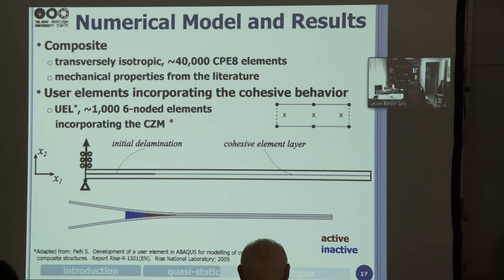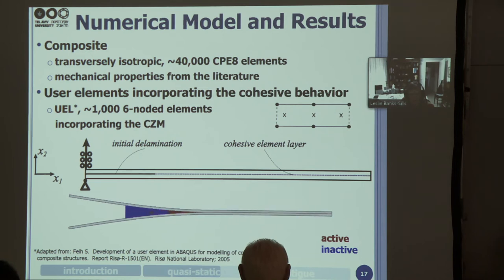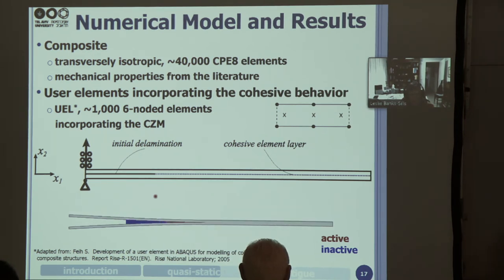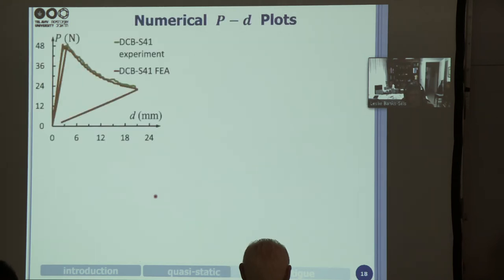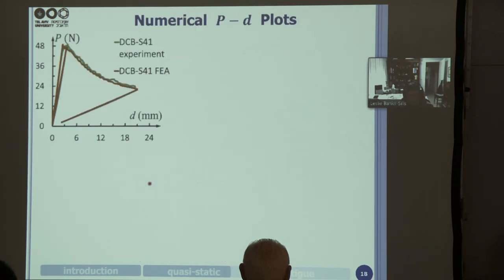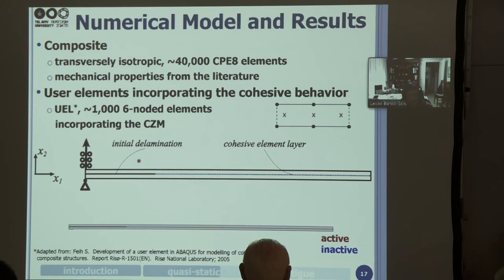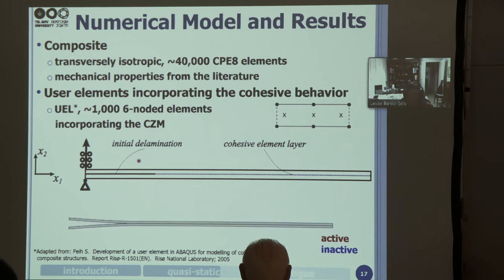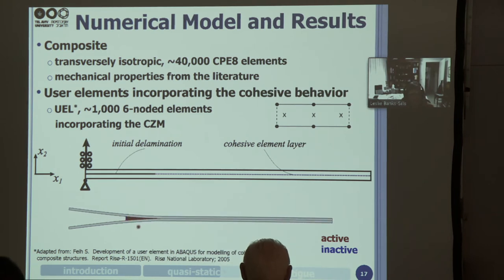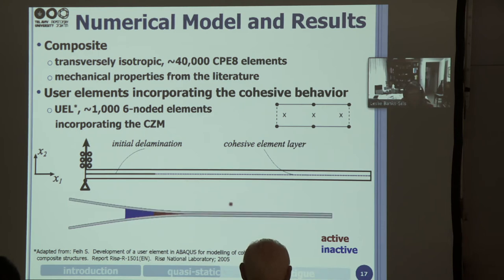And you can see now the propagation, the blue area is where the delamination no longer exists. Maybe I'll play it once more. I should be able to play it once more. Okay, now perhaps. So you can see the active zone where we have the cohesive zone, and soon the fibers are going to start to break, and we have broken fibers and a cohesive zone that's traveling to the right with the tip of the delamination traveling to the right.